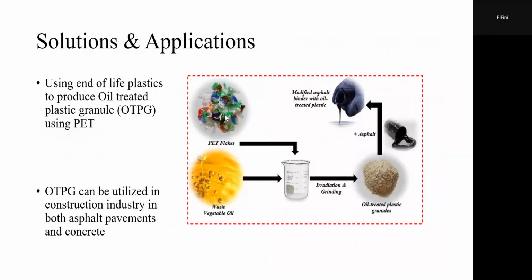You can see these granules, the colorful, they are different plastic. We grind them to this fine powder here, and then we use the oil to coat the surface. You may think why we are coating it with waste vegetable oil. In this case, in waste vegetable oil and many other bio oils, we have molecules that can graft or attach to the surface of plastic. So now you have a plastic that doesn't call itself plastic. So then asphalt may like it because it doesn't see that much of incompatibility. So we call this one oil-treated plastic granules, and that's how it's made. It's a patent pending technology here at Arizona State University, and we're trying to use it in trial roads and sections here.